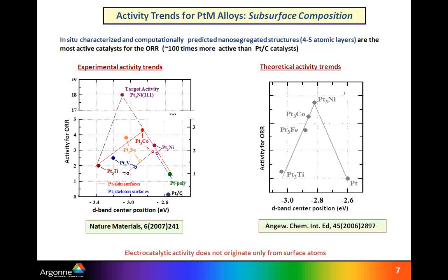On the right-hand side, these are calculations which have been done by Jens Norskov. And again, as in experiment, it was confirmation that platinum-3 nickel and platinum-3 cobalt are sitting on the top of the volcano curves. Now, if I go back to the left-hand side, one can see that we purposely put the activity of platinum-3 nickel 111, which is a couple of times more active than polycrystalline surfaces. All of these volcanoes are established for polycrystalline surfaces.